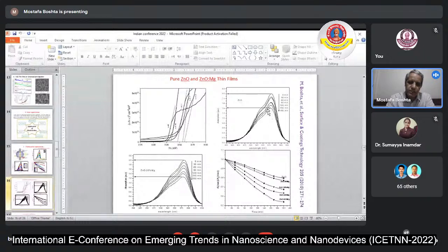If we look here at the zinc oxide, the absorption and decay of the dyes is a little bit high, but when we add the magnesium to the zinc oxide, there is an increase of the absorption and the decay of the dye inside the solution. And we conclude everything here. We can see the difference between zinc oxide and 3% of the magnesium oxide added to the zinc. The difference is a little bit high, and it can be considered a good material for the photocatalytic application and the decaying of some dyes in the chemical solutions.